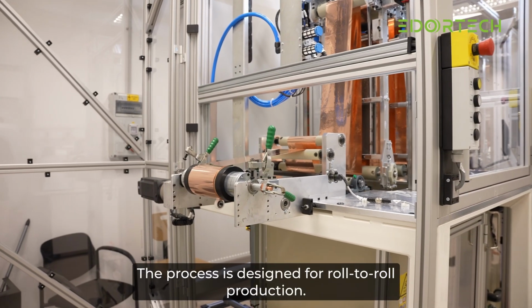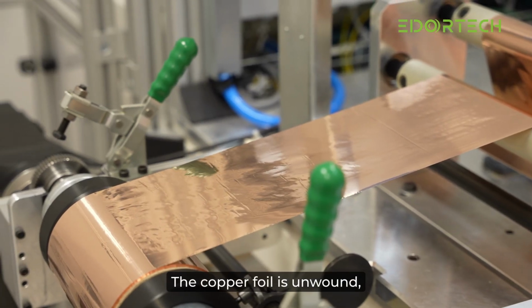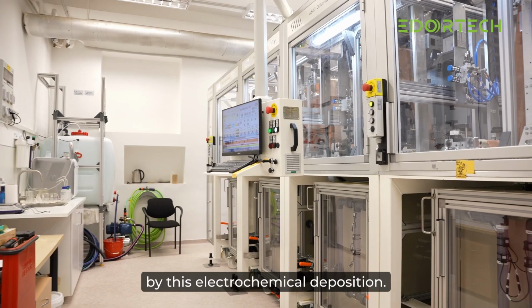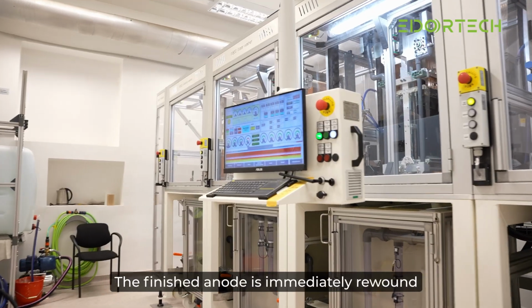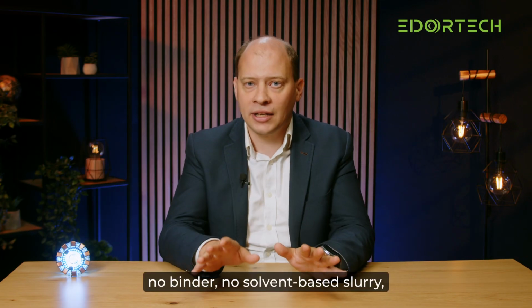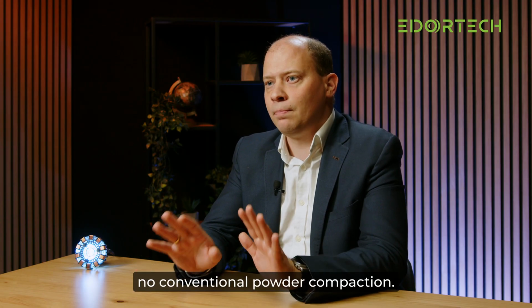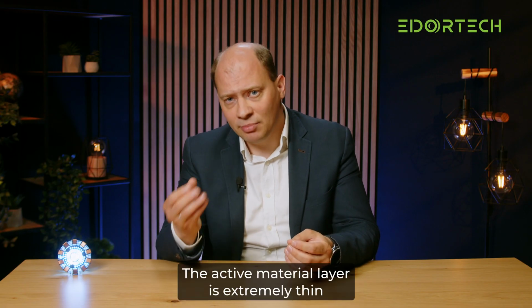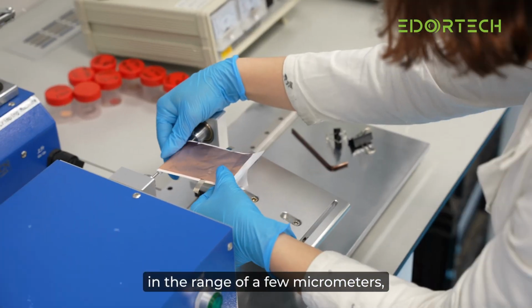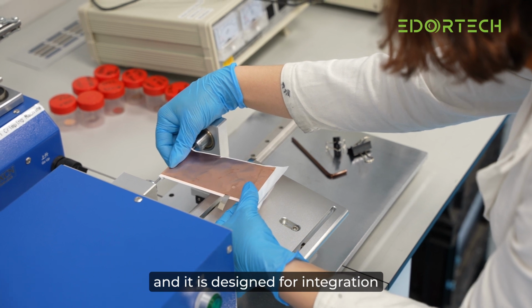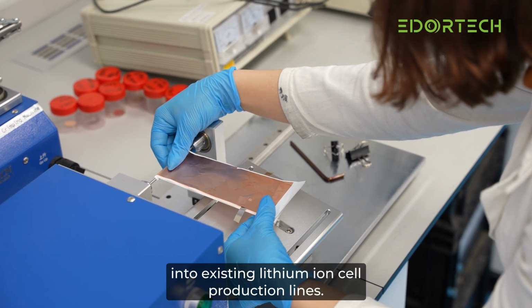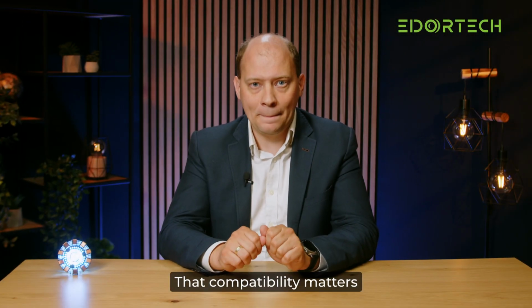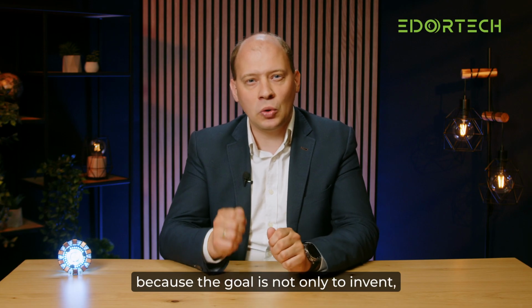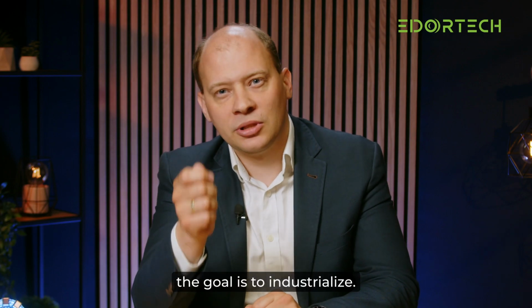The process is designed for roll-to-roll production. The copper foil is unwound, and the metal alloy anode is formed by electrochemical deposition. The finished anode is immediately rewound as a continuous product. No graphite powder, no silicon powder, no binder, no solvent-based slurry, no conventional powder compaction. The result is a cleaner and more direct production route. The active material layer is extremely thin, in the range of a few micrometers, and it is designed for integration into existing lithium-ion cell production lines. That compatibility matters, because the goal is not only to invent, the goal is to industrialize.